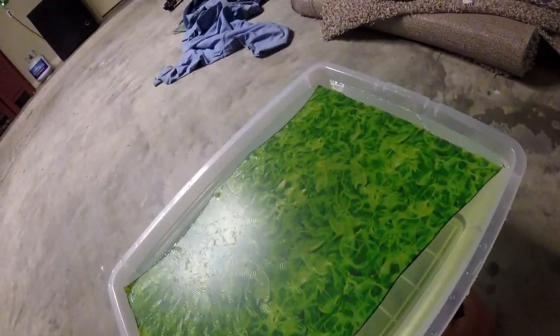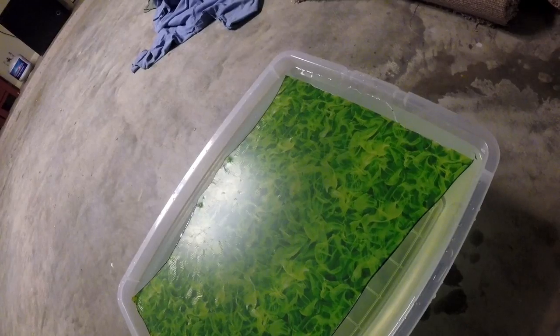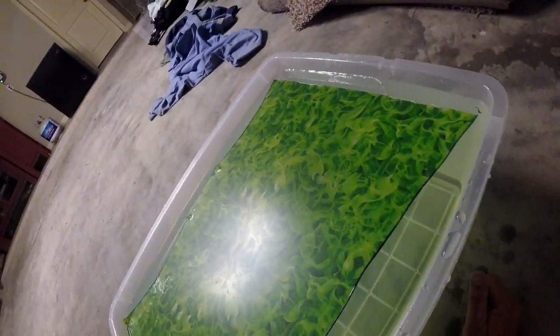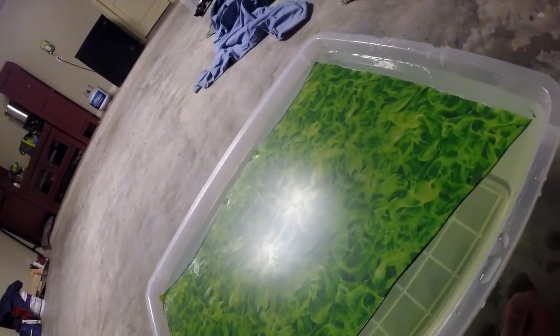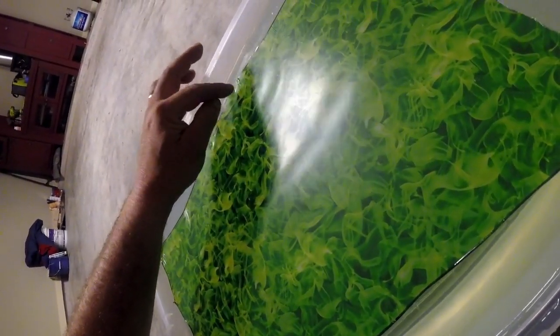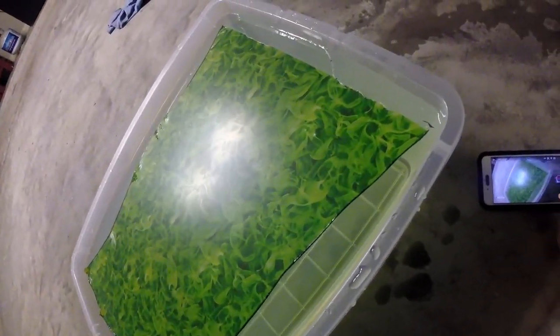Make sure you've got a border around the film. Lucky this piece was big enough that I didn't need a separate border, but if you do need one just tape it out. That's what you're waiting for — see how the wrinkles are going away. Hot water, cold water — I don't really see a difference; one just takes longer. Warm water will tense it up faster. Now it's crystal clear and smooth. There is an air bubble on the edge but since it's on the edge I'm not too worried — you just work the air bubbles out.